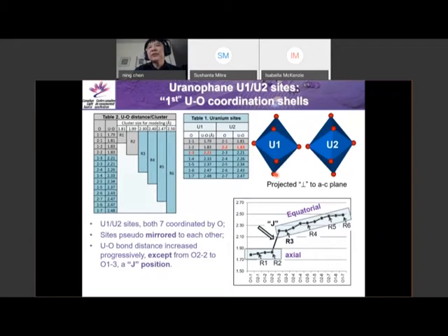On this pseudo-equatorial plane, there are five oxygen. In that way, each of the uranium sites here is coordinated. It's very complicated. And then this is a site, uranium 1 and uranium 2. The oxygen here for each site is numbered from 1 to 7. So 1,1 to 1,7 and 2,1 to 2,7, because the uranium 1 site and uranium 2 site both see the X-ray at the same time.